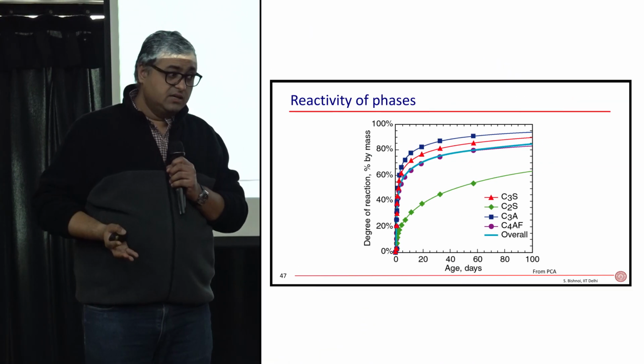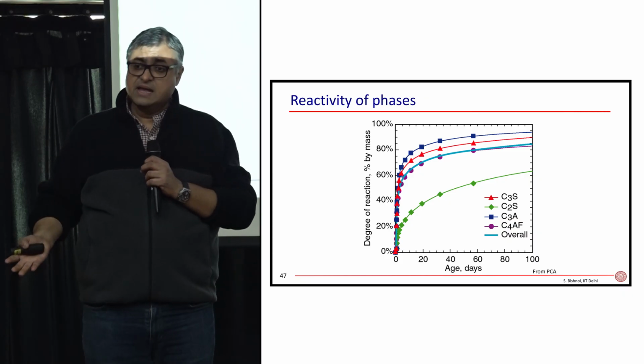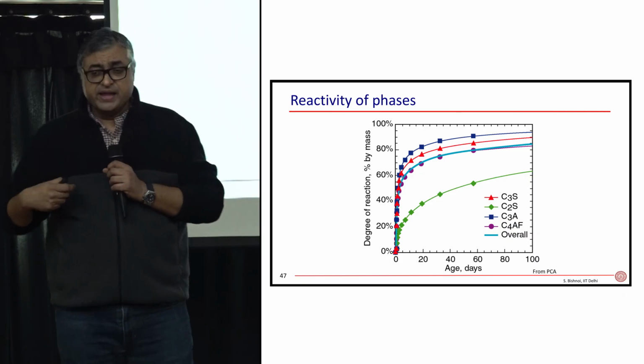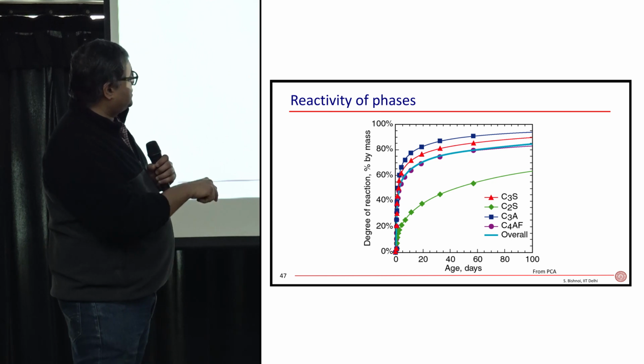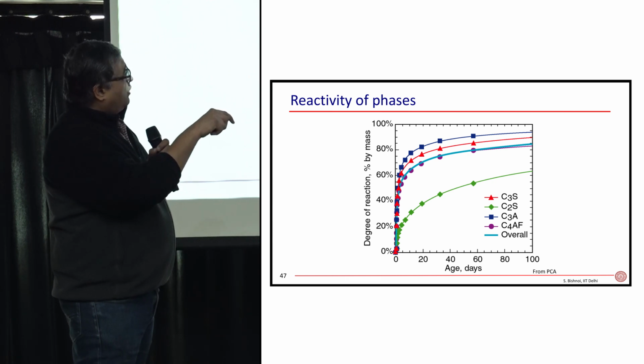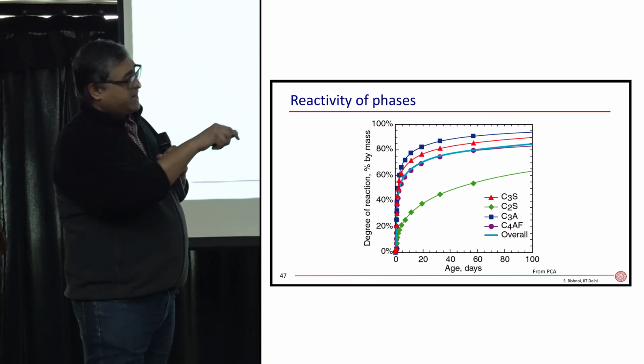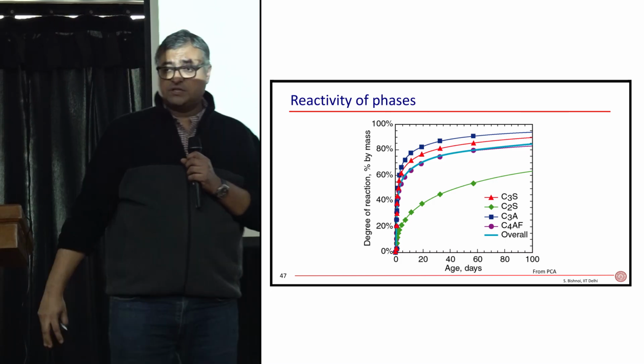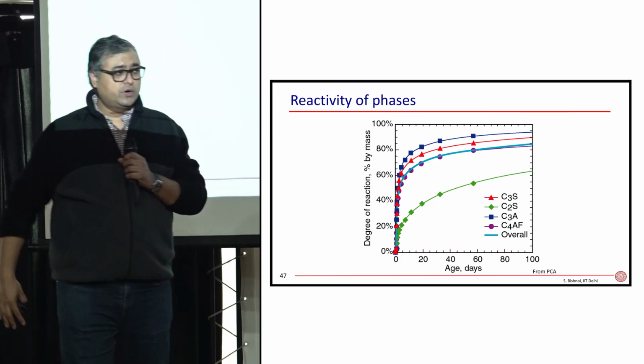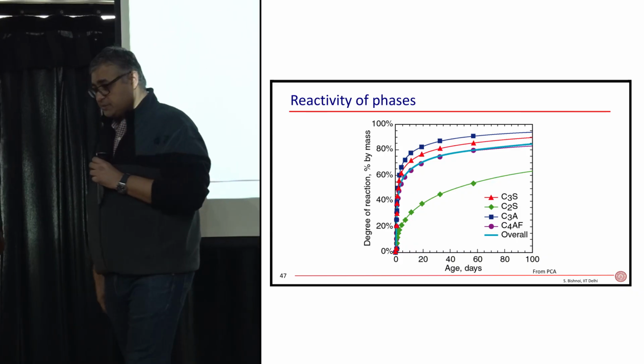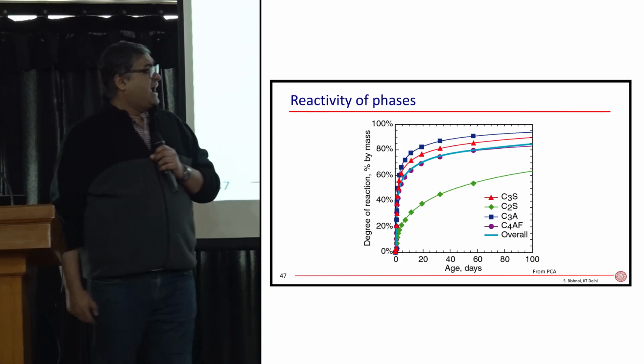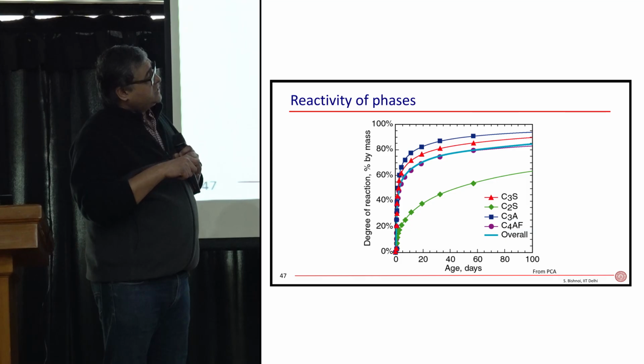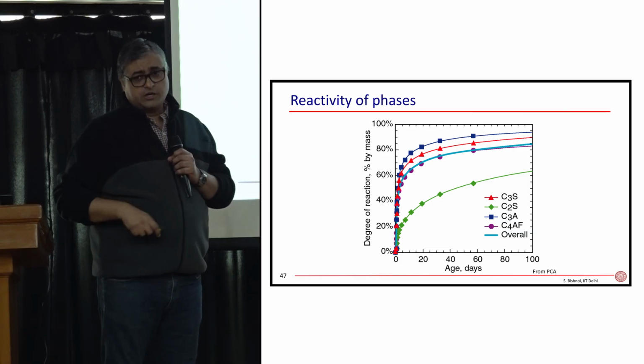But different materials have different rates. Different phases have different rates of reactions. Like I said, aluminate reacts the fastest. So if you measure how much of aluminate has reacted, you'll find it has reacted the fastest. After that comes alite. Alite is slightly slower than aluminate in how much of it reacts, at what rate. And then slowly over time, C2S and ferrite also start to react.